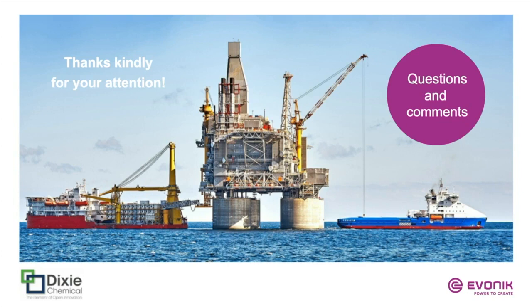Jeff, would you like to add anything just to close out? Yeah, no, I agree. I agree completely. I mean, we've shown that you can really tailor the performance of the finished syntactic foam by the ratio of monoanhydride to dianhydride to allow you to really dial in the properties you need for the specific application. I just want to echo what you said, which is that is really a novel finding, novel observation that I think is going to lend a lot of value as we go forward with this overall project.